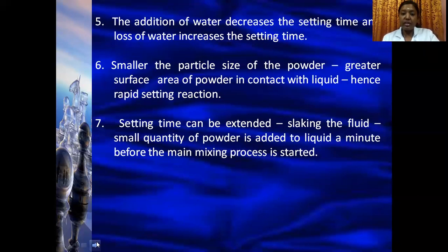Addition of water decreases the setting time, and loss of water increases the setting time. The smaller the powder particle size, the greater is the surface area of the powder that is available to be in contact with the liquid. Hence, more rapid is the setting reaction. The setting time can be extended by slaking the liquid, in the sense that a small amount of powder is added to the liquid a minute before the main manipulation process of zinc phosphate is started.